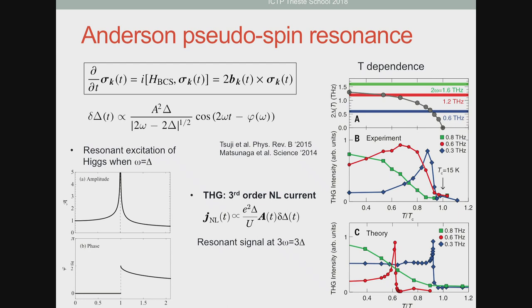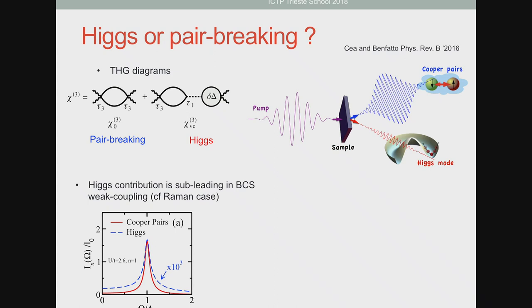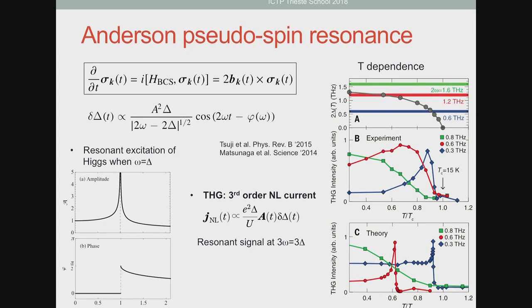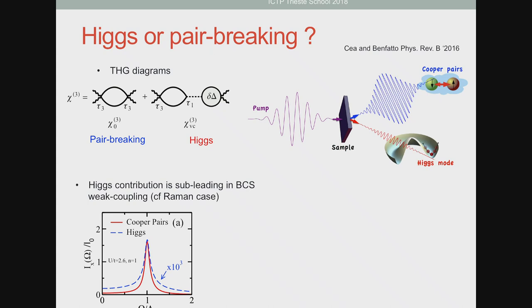We have seen two manifestations of a 2 delta mode, one in the time domain in the form of some transient response that was oscillating at 2 delta, and another one which was a forced oscillation, if you want, but that seemed to be linked directly to some kind of non-linear optical susceptibility. And both of them are at 2 delta. So actually, once you see this and you know a little bit about Raman, there is, of course, an alternative explanation, at least to this kind of measurements. I think it's a bit less obvious for the transient measurement in the time domain. But at least for the third harmonic generation, there is an obvious alternative, which is that it is the pair breaking peak.